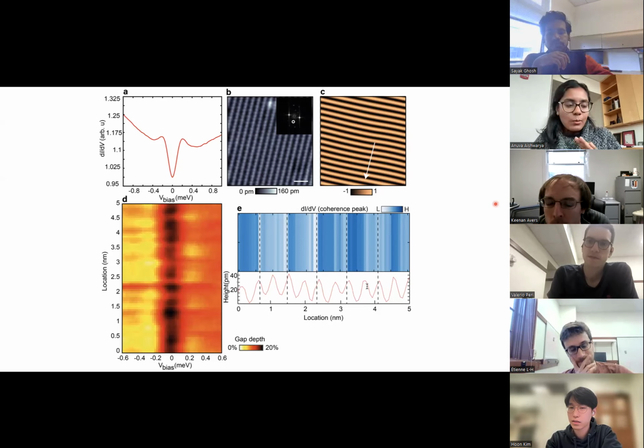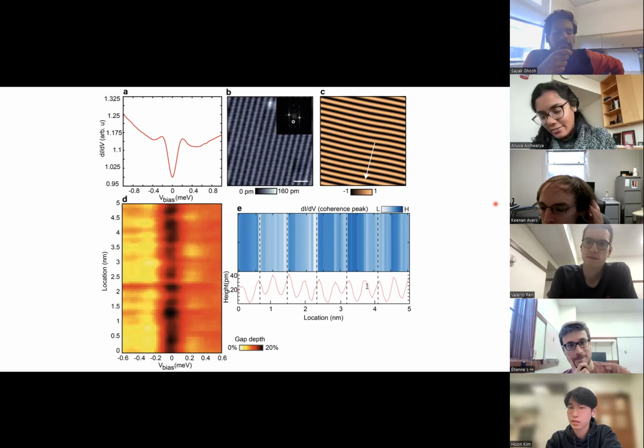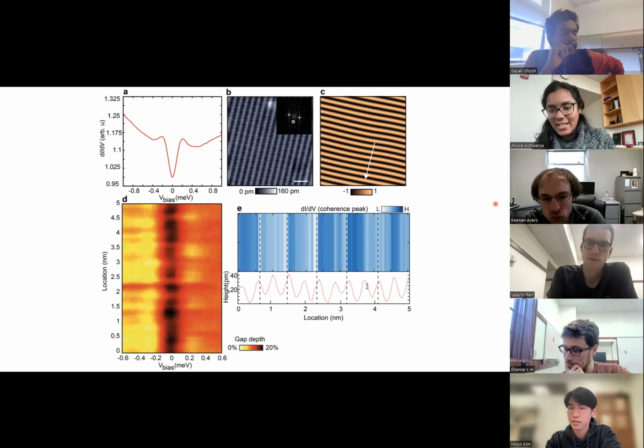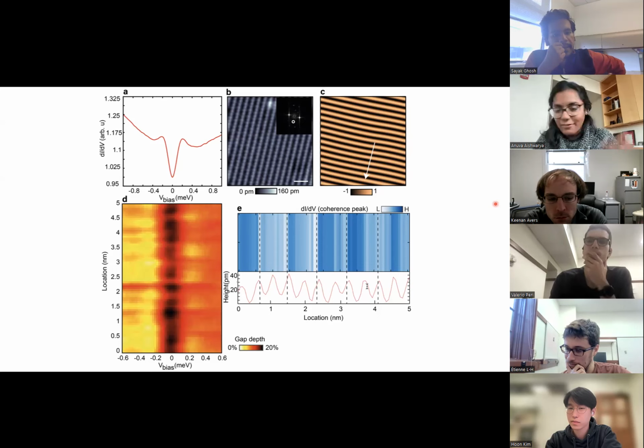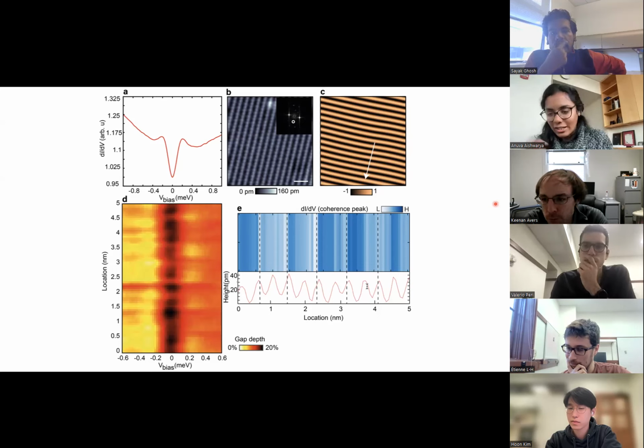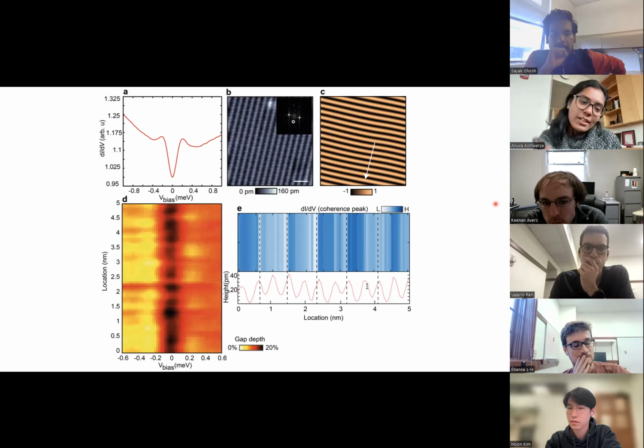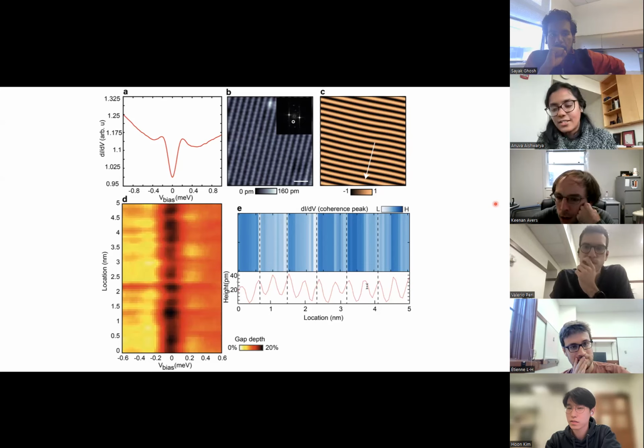So one possible way that we thought of where we did not have to invoke the PDW scenario was, let's say there's a spin density wave, and then you can explain that the spin density wave goes away when you apply a magnetic field. But that case has issues because there is no reported spin density wave in several magnetic scattering experiments. So we cannot go through the spin density wave route. So one way we can reconcile these two is, let's say at the surface somehow the PDW survives above TC for a small range of temperature. That is something that transport would not be able to detect because they're primarily sensitive to the bulk, but it's still an open question.